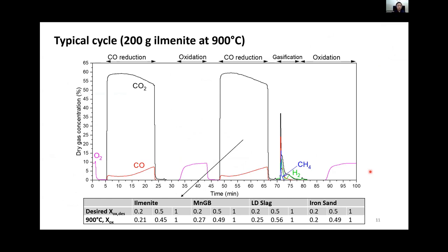Here is a typical cycle. This typical cycle has a first CO reduction, and then oxidation, and the second CO reduction, and then gasification, and then the oxidation. The first CO reduction is to find a suitable time that can reduce the oxygen carrier to a certain reduction degree, or what we call oxidation degree. That means the degree of oxidation of the oxygen carrier.